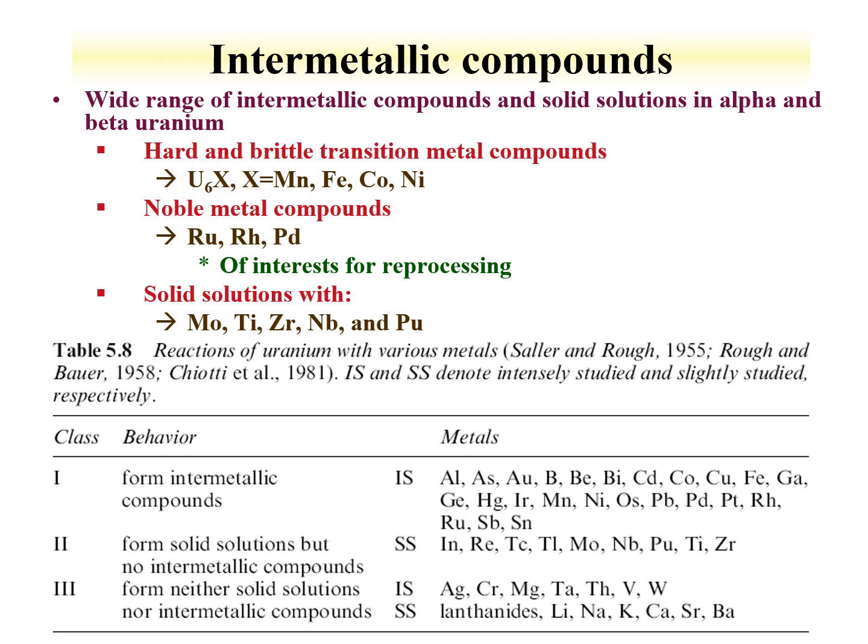So if you had uranium metal against stainless steel, which can occur in a fast reactor, and you started to have diffusion of the stainless steel into the uranium, you would change that uranium metal to this intermetallic compound. Noble metals can also form intermetallic compounds with uranium.